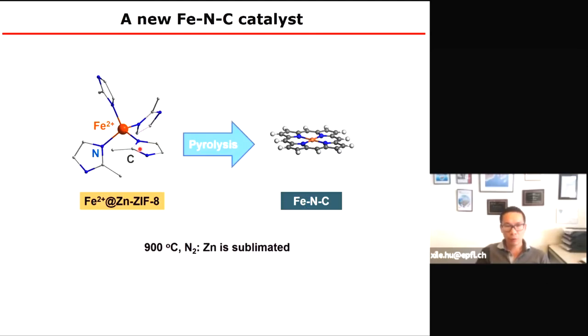In our lab, we were doing some single atom catalysts of this type, so we decided to also study them for CO2 reduction. We wanted to test iron systems. We make our iron-NC compound by pyrolysis of the porous material zinc ZIF-8 with iron doping. At high temperature, the zinc is evaporated, so we end up with just the iron-NC compound.